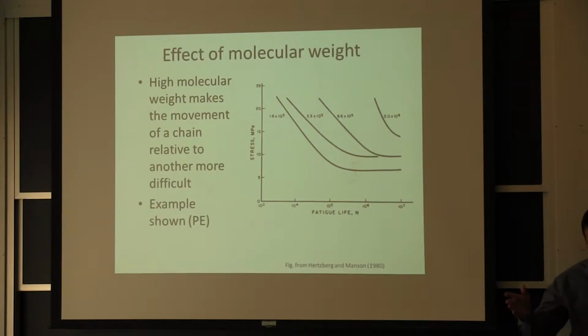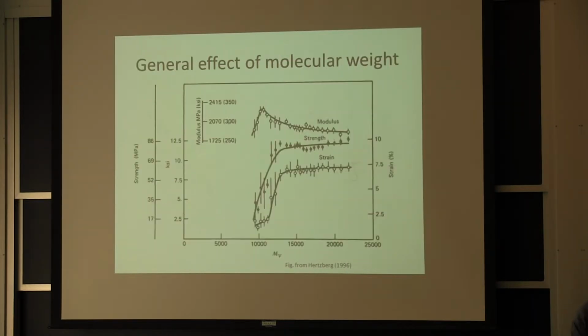If instead of applying the load just one time, I decide to fluctuate it, I essentially accelerate the creep behavior. So with polymers, in terms of studying cracking, it's common to do fatigue loading, so applying a cyclic load as opposed to just a constant load, because you can run your experiment in a couple of weeks as opposed to having to wait 4 to 6 months. It's not perfect, but if you can show, looking after the fact at how the material fractured, that it's fracturing in a very similar way, you have a good justification for it, because you're looking at the same mechanism of separating the crack. And we'll talk a little bit more about how the crack separates in the next lecture.